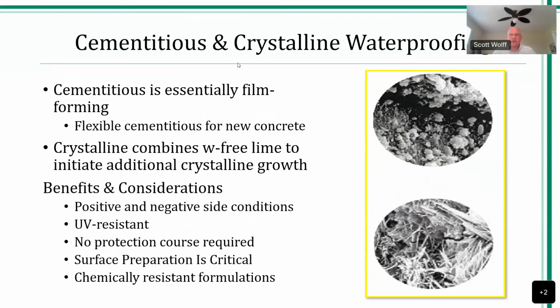Cementitious and crystalline type waterproofings. The crystalline are either found in admixture or topically applied. And then there are flexible cementitious types, which are essentially a film forming type of membrane. What these do is they basically combine with the free lime within the pre-existing concrete and initiate a renewed crystalline growth, because as I mentioned earlier, concrete under high magnification has a lot of pores, and that's what obviously allows water vapor or water to migrate wherever we have a sizable temperature differential or a vapor pressure delta between two sides.